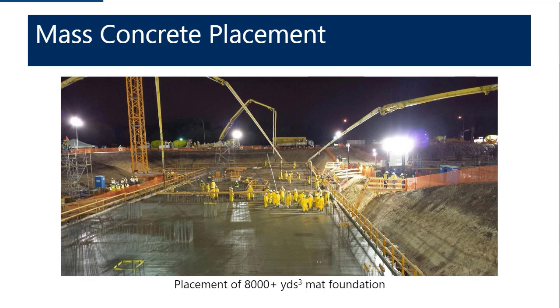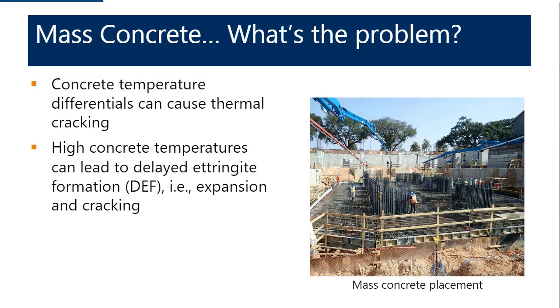And so for some mass elements, that exothermic chemical reaction can generate temperatures up to 160, 170, and in some cases, if precautions aren't taken, up to 200 degrees Fahrenheit, which is a significant amount of heat when you compare that to boiling water, for example. And so what's the problem? The big issue is cracking. And so the two things that we want to think about is thermal cracking and a phenomenon called delayed ettringite formation, which can occur later, that can also cause cracking.